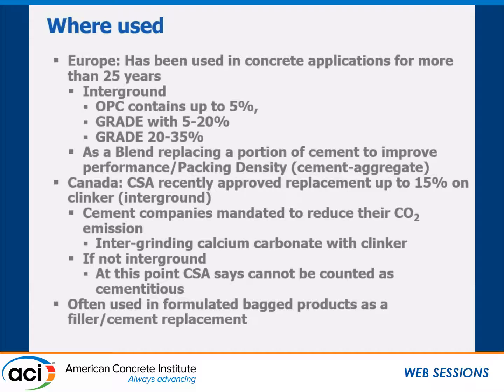In France and Europe, CEM2 cements have 5–20% limestone, and another grade has up to 35% clinker reduction. The big difference is that those CEM2 cements in Europe are not ground very fine — they have blends very similar to regular OPC. Here, our cement companies when creating PLCs are grinding them to an equivalent performance of a regular Type 1 cement, so they are equivalent in performance, as shown in many presentations.